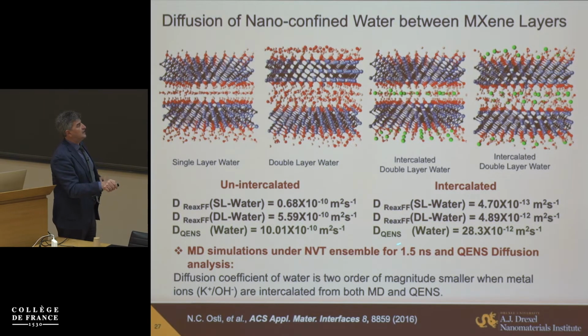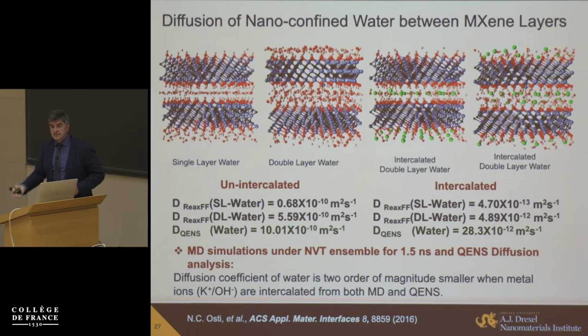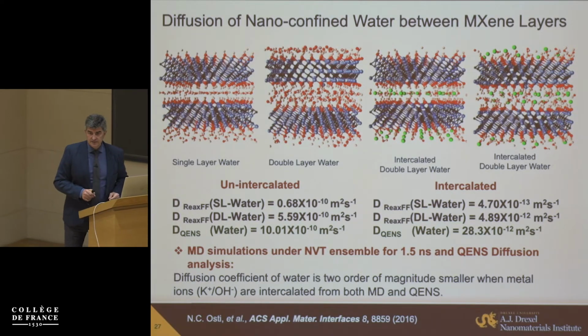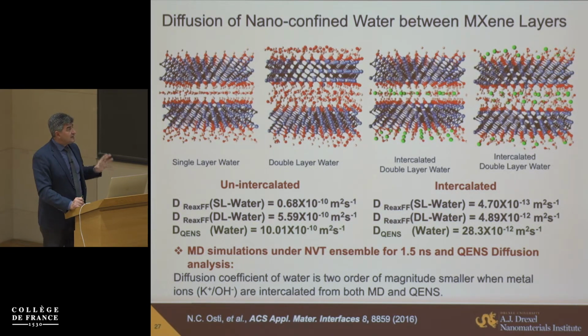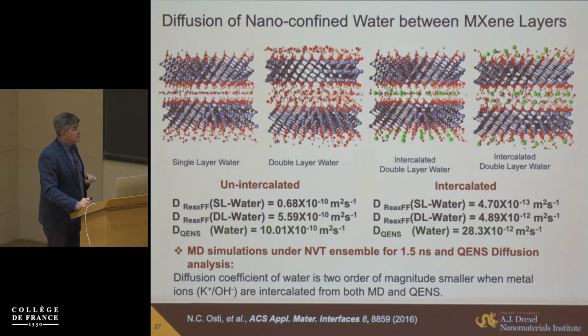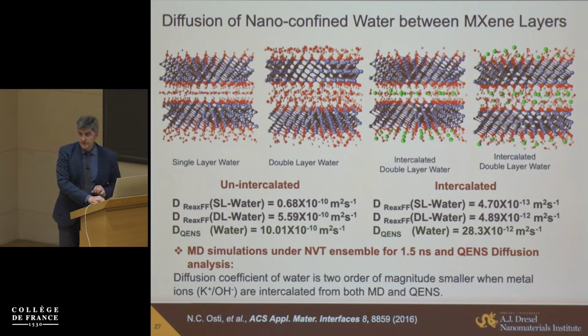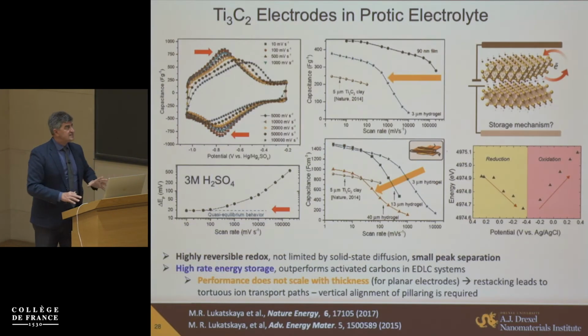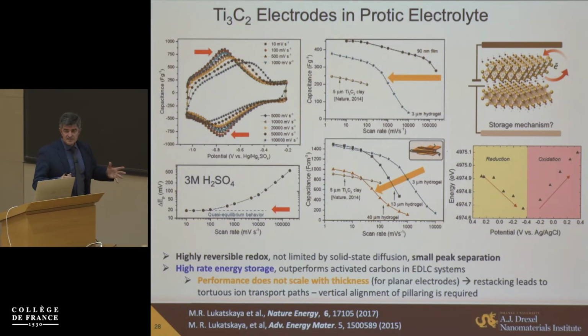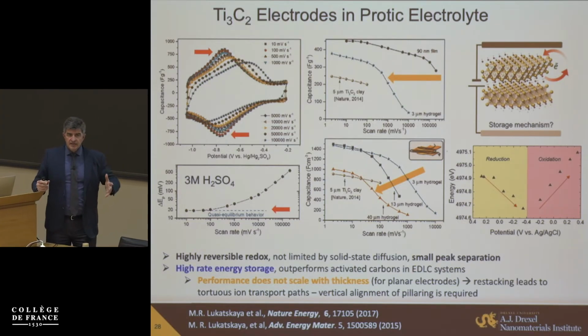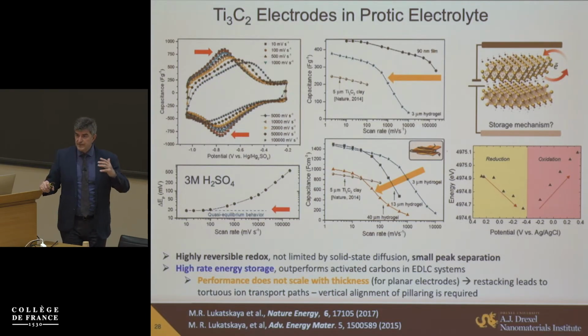We did it by quasi-elastic neutron scattering technique, by prediction, by ReaxFF simulation, but also we measured very similar behavior by using simple electrochemical impedance. So we actually greatly slow down this water between MXene layers, so it behaves differently here. Now, we start slowly understanding how the system behaves here. Then the question arises: can we really have fast redox at very high rate and still keep a redox reaction when we have high conductivity of MXene and we have ions delivered here? And the answer is yes.